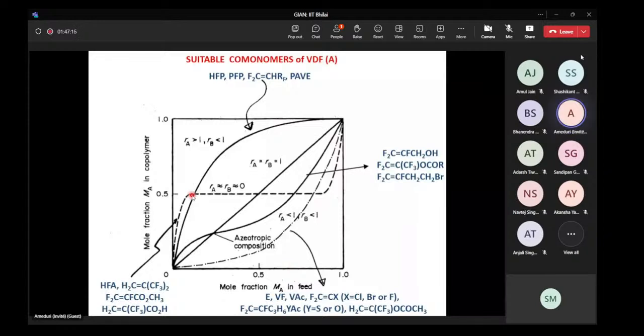In this case, this is alternating copolymer. So this is the case of hexafluoroacetone. Central Glass in Japan studied a lot of copolymers of hexafluoroacetone and VDF for optical fibers. Hexafluoroisobutylene, this trifluoroacrylate, and this compound, which is more or less, I say, the cousin of acrylic acid. Acrylic acid homopolymerizes very well, but the presence of this CF3 here totally inhibits its homopolymerization. However, it copolymerizes very well with VDF.